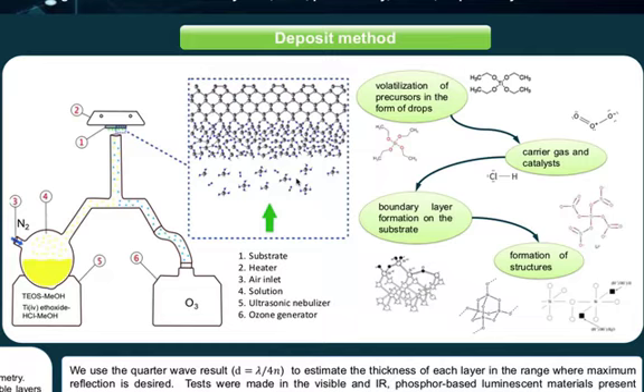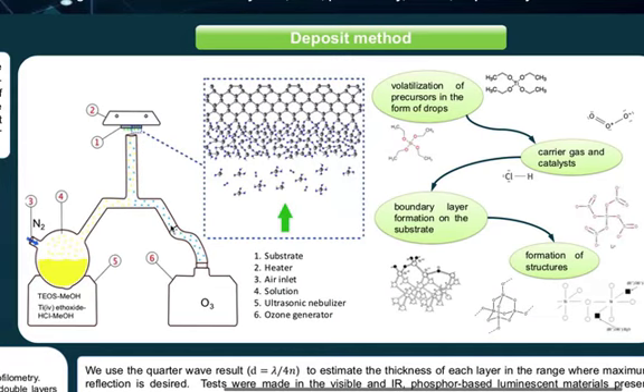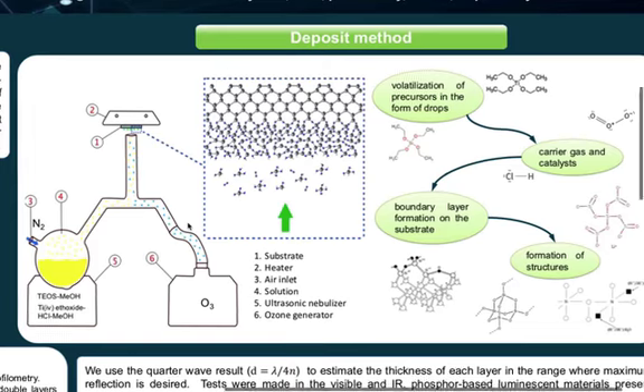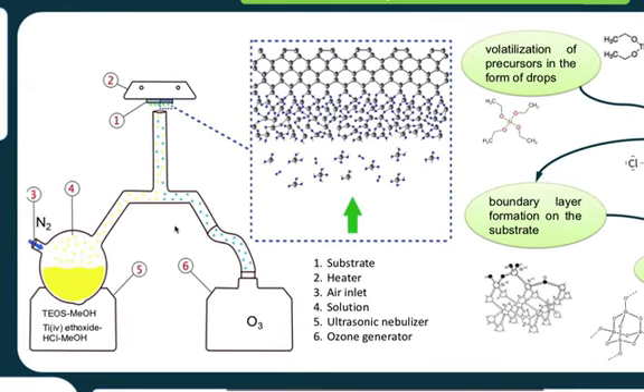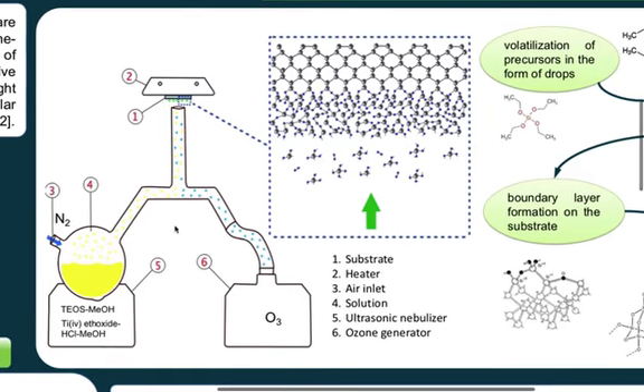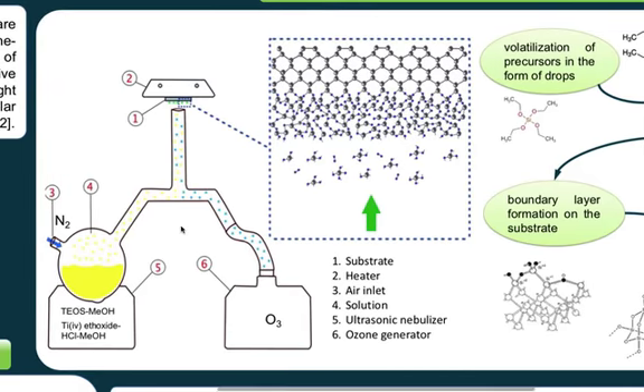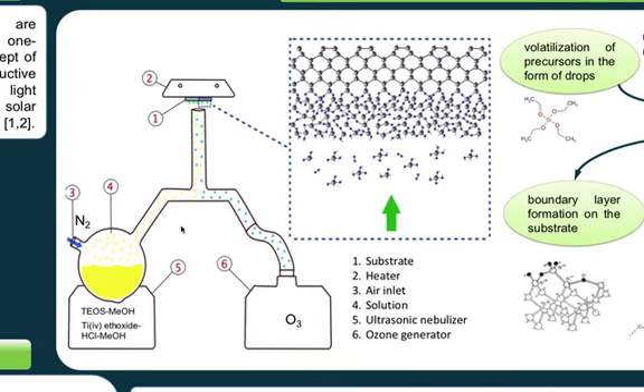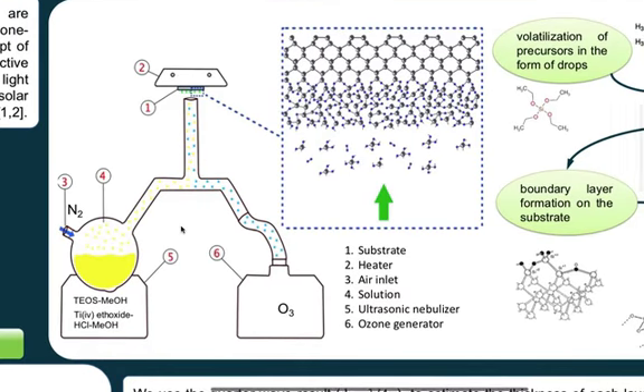Here we have a sketch of the reactor and the process that is followed. For the deposit of the alternate layers, this deposition method offers several advantages over methods such as MBE, PLD, or sputtering, since it does not require vacuum pressure or high temperatures, greater than 100 degrees, and the system can be modified to fit the needs of the deposit.